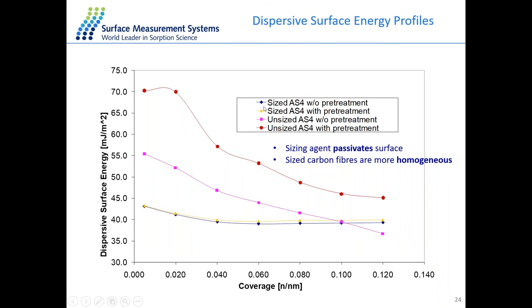And in case of the sized carbon fiber, after applying the sizing agent, the surface energy for both of the carbon fibers, which are the yellow and the blue lines here, shows the surface is passivated with the sizing agent, and the sample becomes more homogeneous, with the surface energy on the samples at almost the same level of energy. So the sized carbon fibers are more homogeneous compared to the unsized carbon fibers.